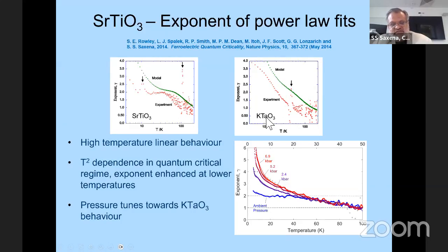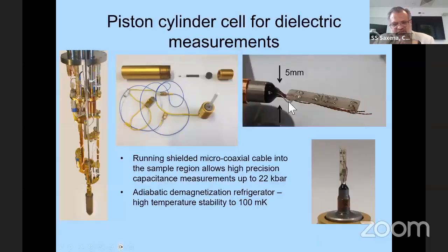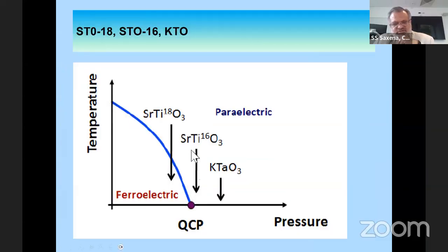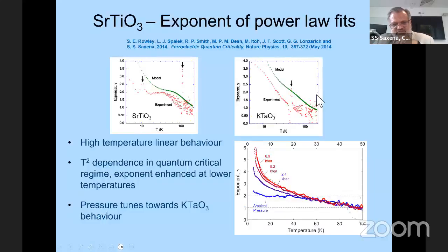But if you look at potassium tantalate, you find that it doesn't order because it's further away from this thing. But if you take strontium titanate and you plot the same thing here, but you apply pressure and you push strontium titanate to look more like potassium tantalate. See, it looks like that. So here, as we had this picture before, by using pressure, you push this to here. This is done here with the same data on the same input. It's all on one material, which starts to look like that.